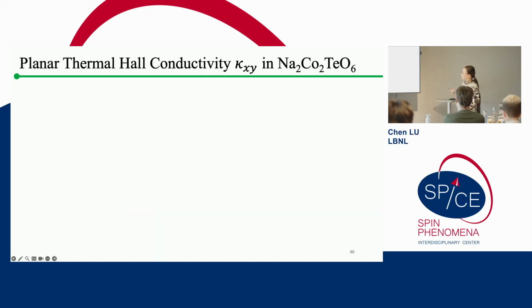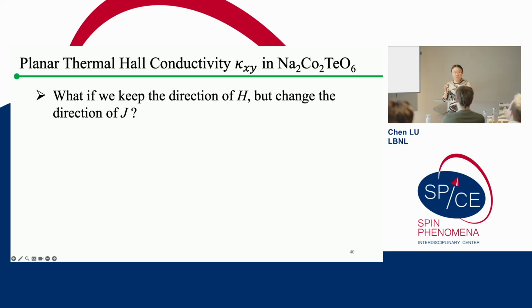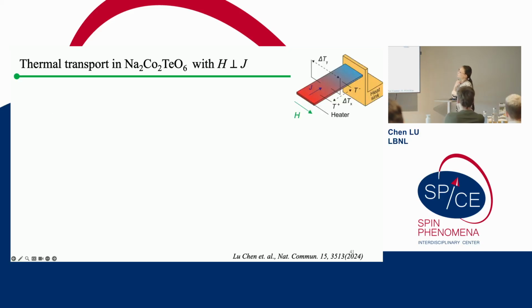At this point, what we want to know is, I only did the measurement with one single planar configuration, which is the field and the current parallel in the sample plane. So how about we try other measurement configurations of a planar thermal Hall, which means what if we keep both the field and the current inside the sample plane, but perpendicular to each other? What will happen? Can you still have a thermal Hall effect or not? Now, in order to have a better quantitative comparison, we did this measurement in 2 sets of samples that were actually cut from the same mother sample, to reduce the sample dependence and be more homogeneous compared to each other.